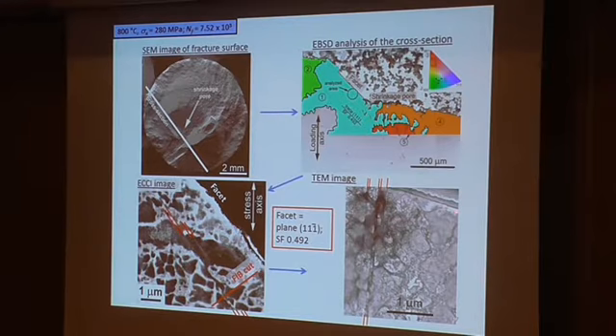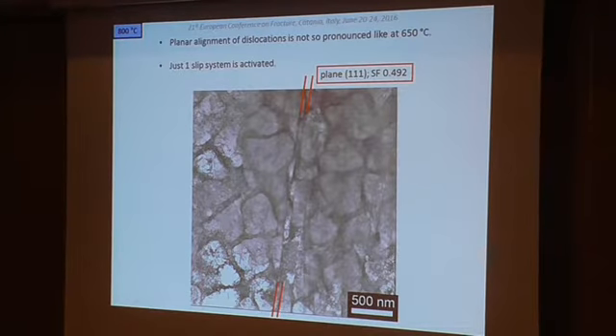And here is an image of the foil, and you can see nice planes with shearing of precipitates with significant dislocation density. And again, this shearing is on a slip plane with very high Schmid factor. Here is another image of this area where I can conclude that planar alignment of dislocations is already not so pronounced like at the previous temperature. So in this case, we had just one slip system activated, but there are already more dislocations in channels of gamma and also in interfaces of gamma prime.